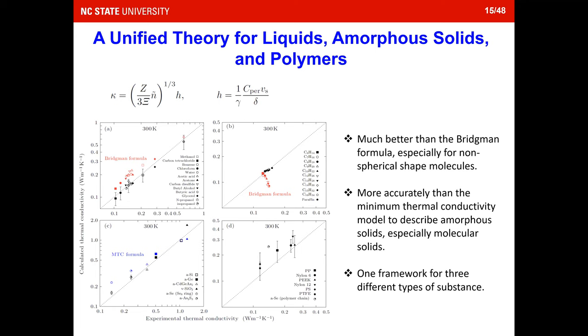On panel C, you can see that using Cahill's minimal thermal conductivity model, you can estimate the thermal conductivity in certain types of amorphous solid, but our model actually predicts pretty well. So basically we seem to have found one framework to describe three different types of substance, right? Liquid, amorphous solid, and polymers. And we're using the thermal resistance network model to describe it, which seems a pretty easy to understand theory. Hopefully we can apply this theory to more materials and try to better understand what really happens in liquid, amorphous solid, and polymer in terms of thermal transport.